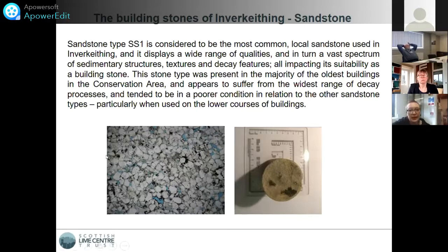So this image on the left-hand side here is a thin section image through the sandstone sample, which is on the right-hand side here. In the thin section sample, we get the thin sections impregnated with a blue dye. So all those blue areas that you can see are actually pore space, or the lighter blue areas are pore space, clay, that has absorbed some of the blue dye. But the reason we do that is it gives us a really good visual indication of the porosity within these sandstones, and that's such an important factor when you're considering your replacement.